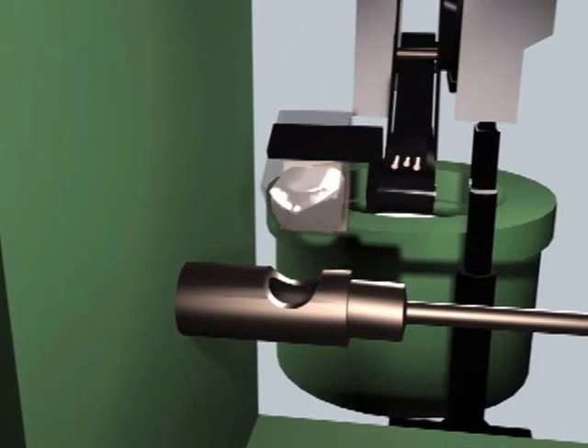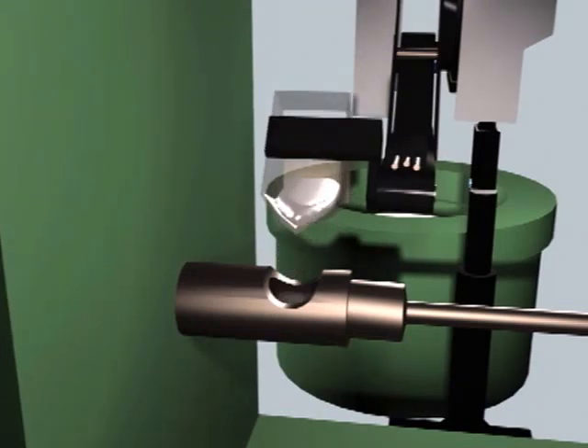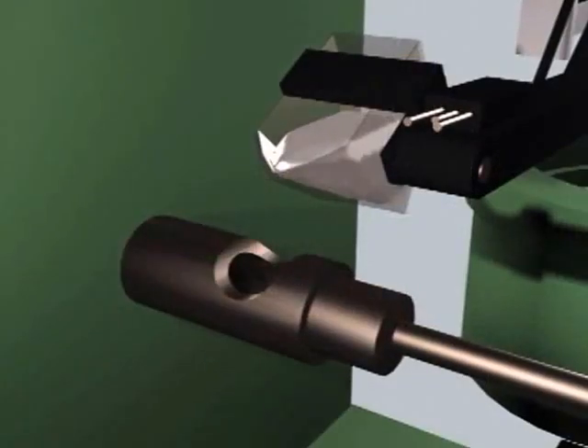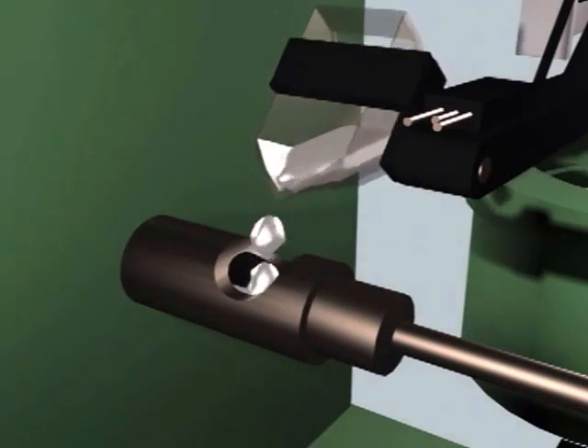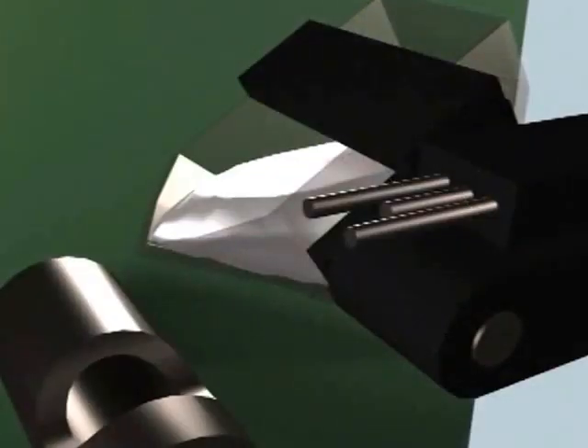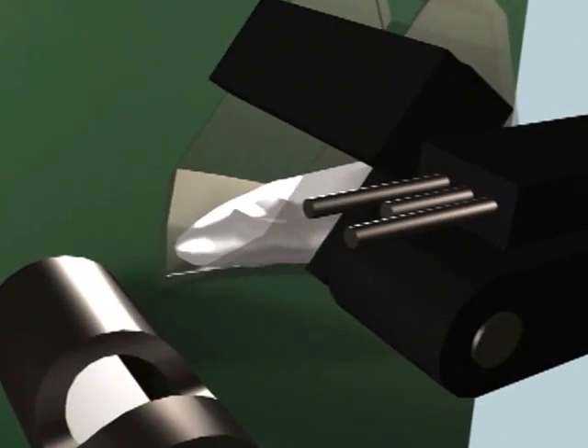The intermediate positions and speeds are responsible for controlling the rate that the metal is delivered into the cold chamber. The limit to how fast the metal can be poured is determined by the size of the pour hole and the shape of the dipper. Experimentation is the best way to determine what speeds and positions to use.